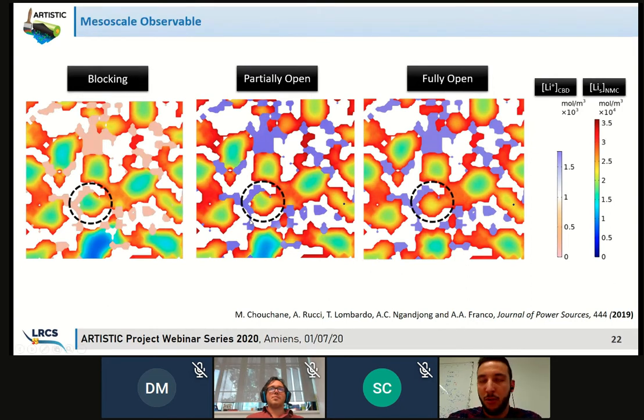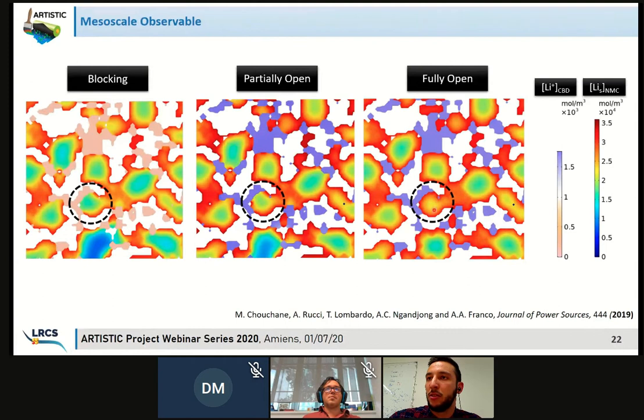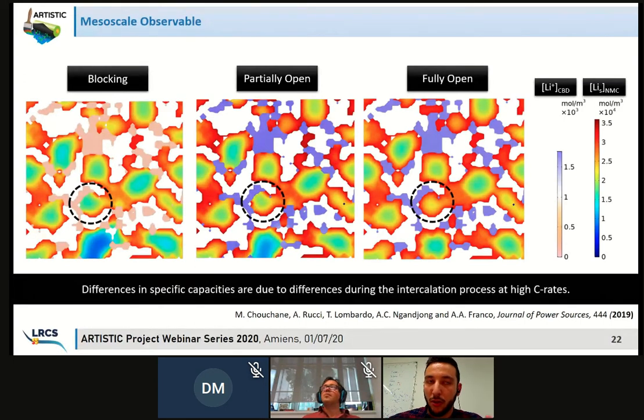So if we focus on this given active material particle, you can see that in the blocking case, the distribution of lithium is really inhomogeneous, whereas for the fully open case, you can see a perfectly homogenized concentration. And this is all due to this CBD here, which is preventing the lithium ion to access the active material and to intercalate at its interface. So that's why it's really a powerful tool, because it can explain macroscopic observables such as specific capacities, thanks to mesoscale effect of the morphology of CBD, because here the CBD will prevent the access to the active material particles, and then you will have a gradient of concentration, which will lead to higher polarization throughout your electrodes, and then less capacity in the end.